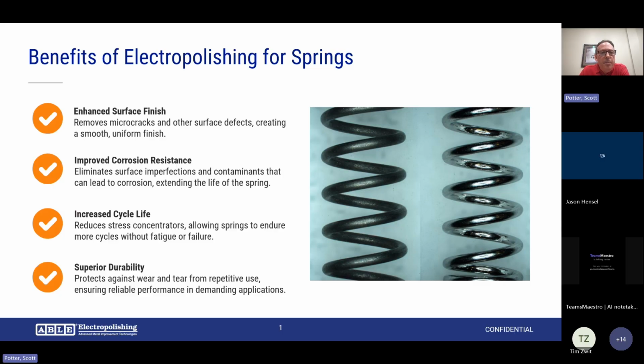Benefits of electropolishing for springs. The big thing with springs is removing micro cracks that develop during stress from forming. We want to make sure that you remove those initiation sites where premature failure can occur. Improve corrosion resistance. The electropolishing improves corrosion resistance by 30 times compared to that of passivation.